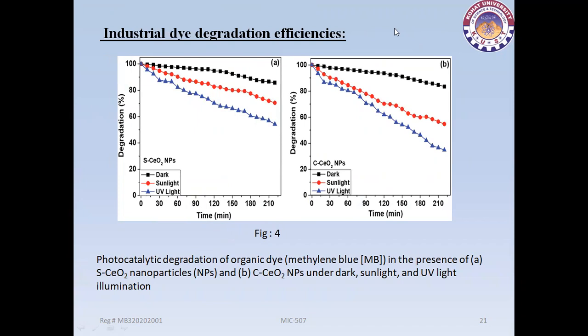Industrial dye degradation efficiency. The photodegradation of the organic dye methylene blue in the presence of the prepared spherical and cubical cerium oxide nanoparticles was examined under dark, sunlight and UV conditions, and the results are depicted in figure 4a and b. Generally, photocatalytic dye decolorization of methylene blue in the presence of nanoparticles tends to increase with the passage of time. Both samples showed minimum degradation in dark condition, with only 7% degradation efficiency obtained for spherical cerium oxide nanoparticles, whereas the degradation efficiency of cubical cerium oxide nanoparticles was 17%.